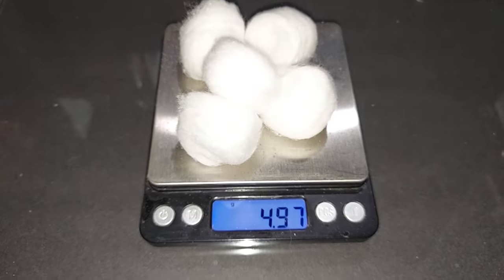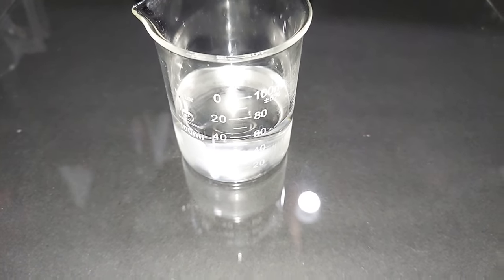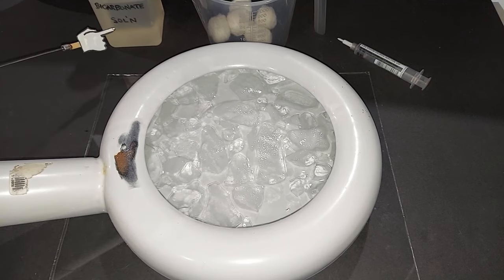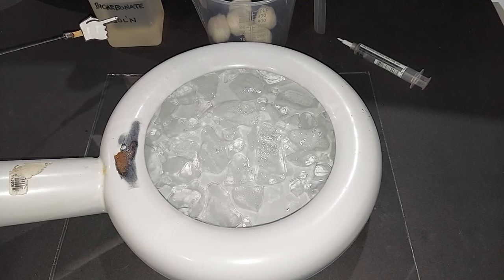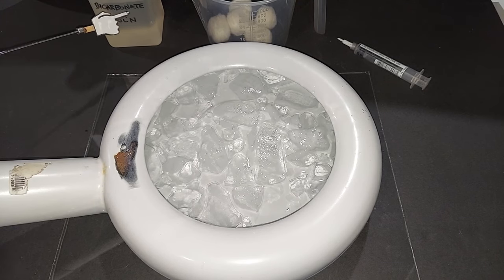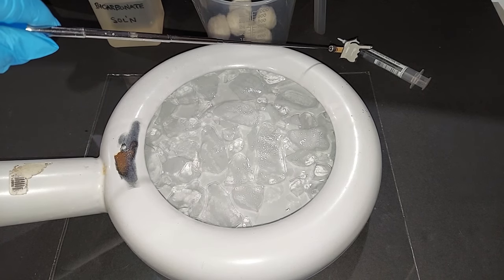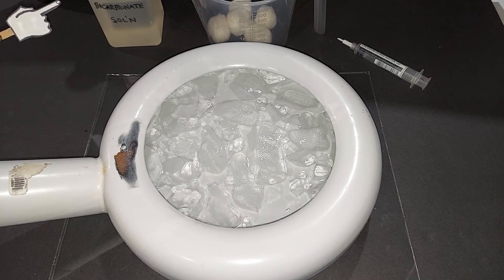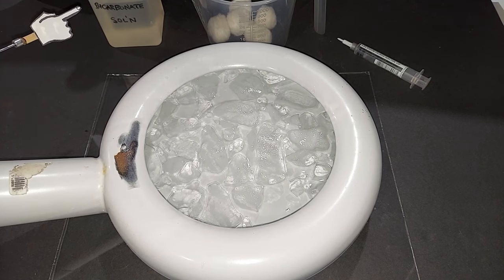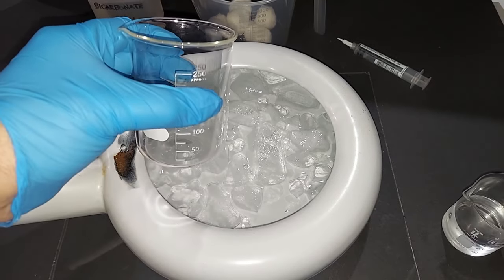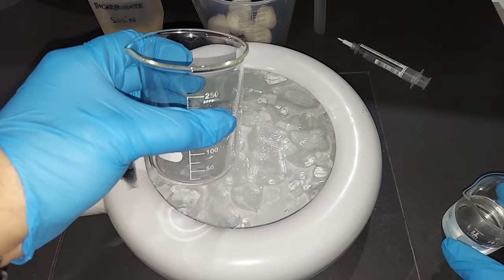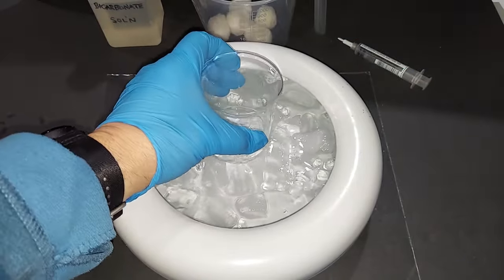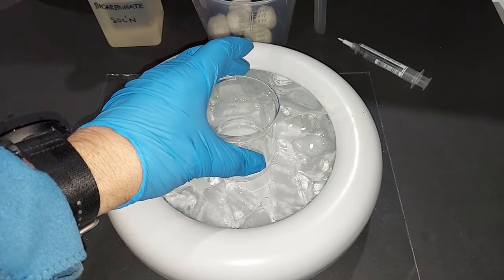Close enough to our five grams of all natural white cotton, 50 milliliters of 70 percent nitric acid, 100 milliliters of 98 percent sulfuric acid. Here's my setup: ice water, bicarb solution for emergencies, my cotton five grams, and a syringe to transfer the sulfuric acid into the nitric acid slowly. The sulfuric and nitric acids have been in the fridge for approximately two hours so they're nice and cold. We start by pouring the nitric acid into the 250 milliliter beaker.